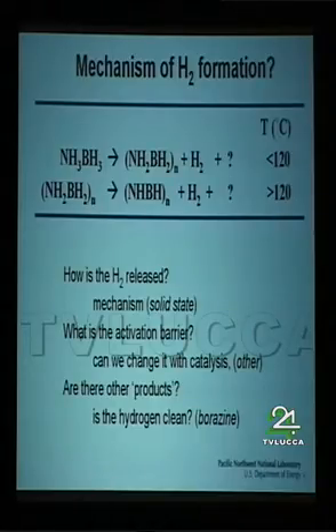And then, if we know something about the mechanism and the activation barrier, are there some catalysts that we can consider to try and improve the kinetics, or some other properties that can be used to enhance the rate of hydrogen release? And are there other products? There are reports that when you heat this up, borazine is formed, and borazine is isoelectronic with benzene and boils at around 50 degrees, so it's not something you want to have in your hydrogen stream if it's going to a fuel cell.